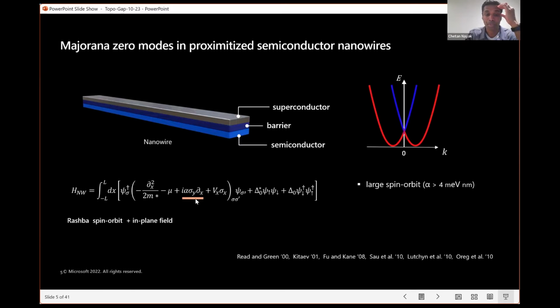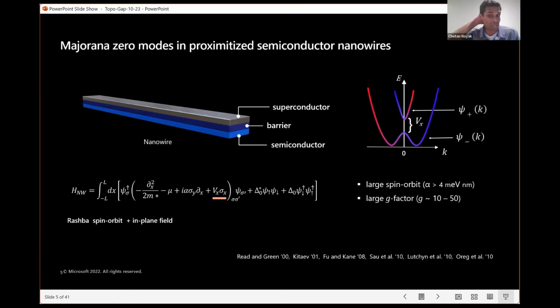Then there's a spin-orbit coupling, okay? And we need large spin-orbit coupling. When the spin-orbit coupling is large, the bottom of the conduction band can get split into two helicities, which look like this. And when we say large, we mean spin-orbit coupling larger than 4 meV nanometers. We also need a large g factor, a g factor of like 10 to 50. What that means is when we put in a magnetic field along the wire, it will open up a gap at zero momentum that splits those crossed dispersions.